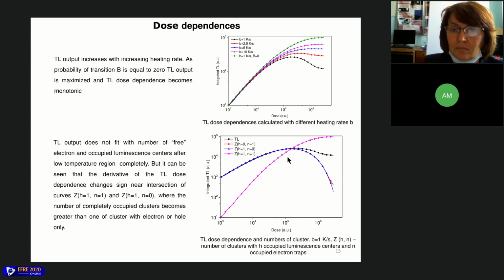In the second figure, the TL output doesn't fit with the number of free electrons and occupied luminescence centers after the low temperature region completely. But it can be seen that the derivative of the TL dose dependence changes sign near the intersection of curves with the state of cluster characterized by one hole and one electron and the state with one hole only. At that intersection point, the number of completely occupied clusters becomes greater than that of clusters with electrons or holes only.